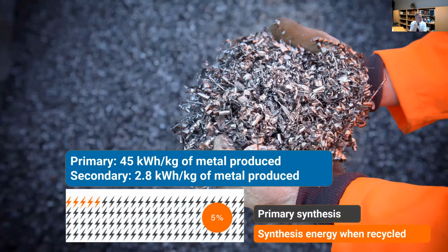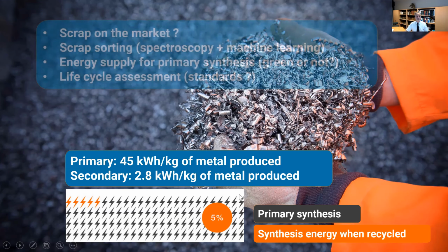So let me, in the last few minutes, leave the steel part. And I apologize that I spent so much time on steel, because simply the leverage of steel production is so incredibly high. But aluminum is very exciting too. Let me just remind you of this simple thermodynamic fact: in the primary production, which is done by electrolysis, we talk of 45 kilowatt hours per kilogram of metal produced for aluminum, because the bonding between aluminum and oxygen is so incredibly strong. So the enthalpy is so high. The secondary production, that means remelting it from scrap, however, comes at very low cost because the melting point of aluminum is, at 660 degrees, low.